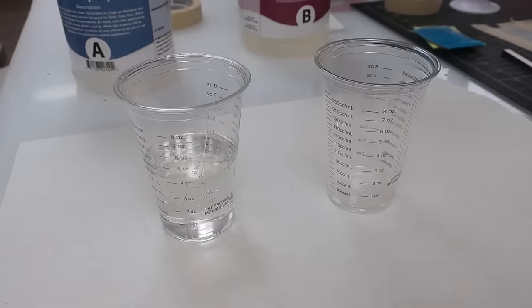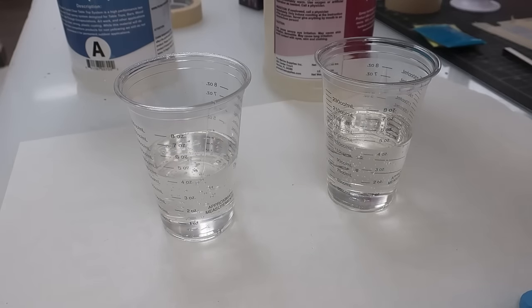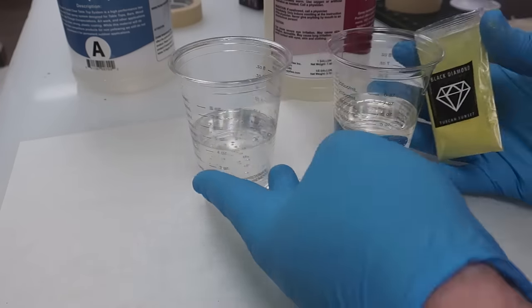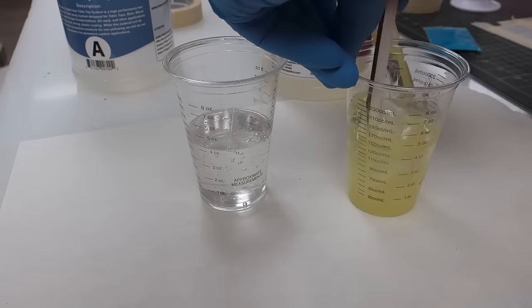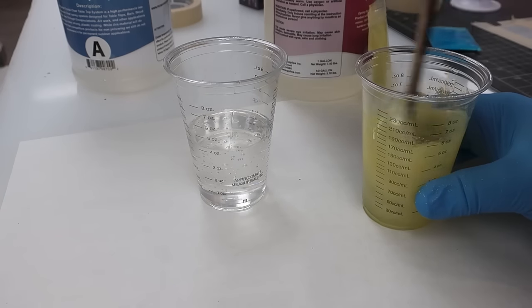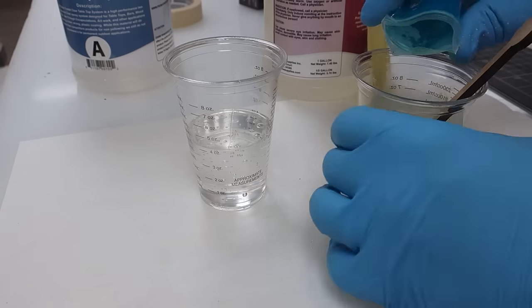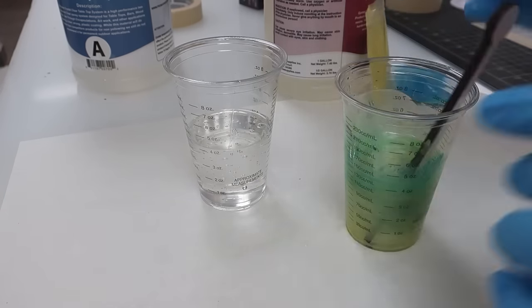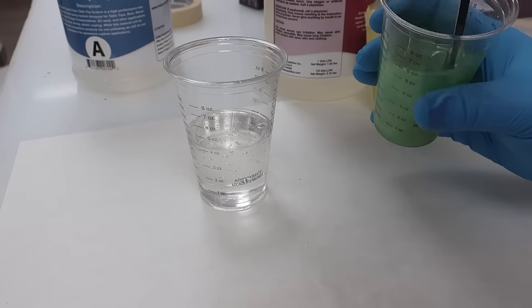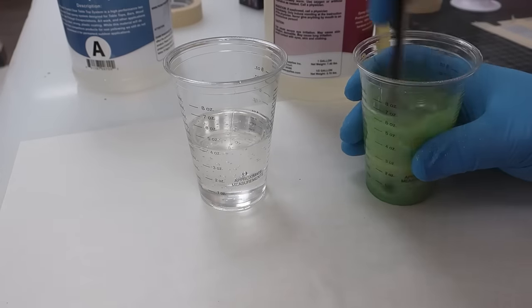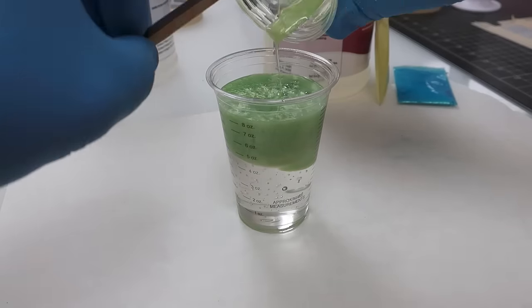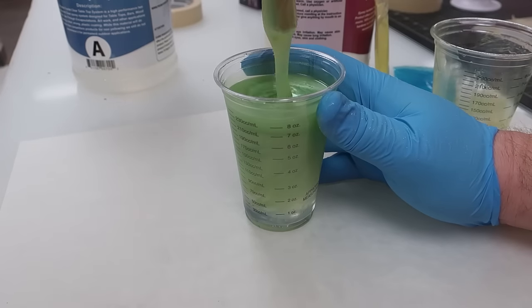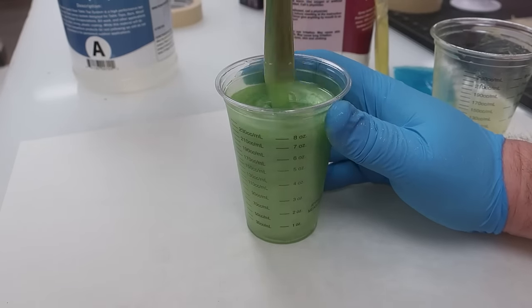The main difference is that this type of epoxy requires two parts to be mixed to activate versus using a UV light, in a 1-to-1 ratio, mixing an equal amount of each. I have poured an equal amount of part A and part B into separate clear cups. I will add a pigment to one side if desired, mix it in, then pour them together, and mix for about 5 minutes straight, as there is plenty of time before it cures.